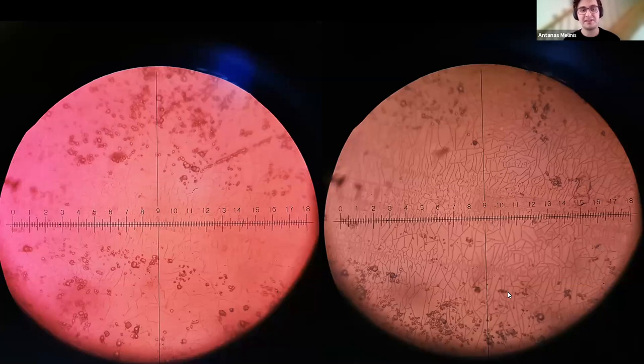It also differs in intensity. In some places it can be more concentrated, or the flakes could be sparser. So it suggests that there are points of stress, and crizzling is not just caused by uniform collapse of the weathered layer or just the tension between the surface and the parent glass, but also the internal structure differences within the layer itself.